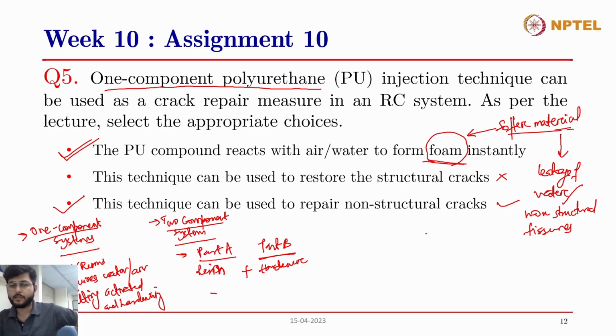cannot set when there is water present over there, and so therefore epoxy doesn't behave well. It is immiscible in water. It doesn't behave well in the presence of water, and therefore for it to set, the leakage of water has to be stopped first, and therefore PU injection is done first, and then epoxy injection is done later, and then this will complete the total repair work.